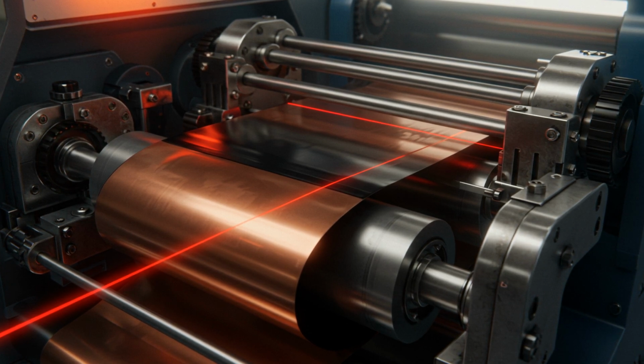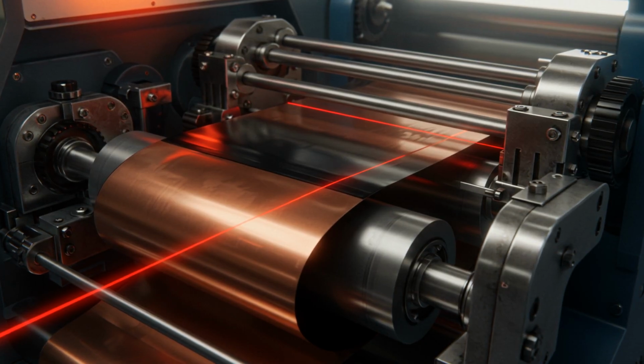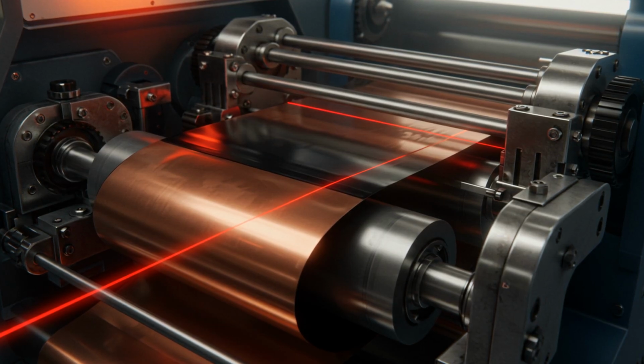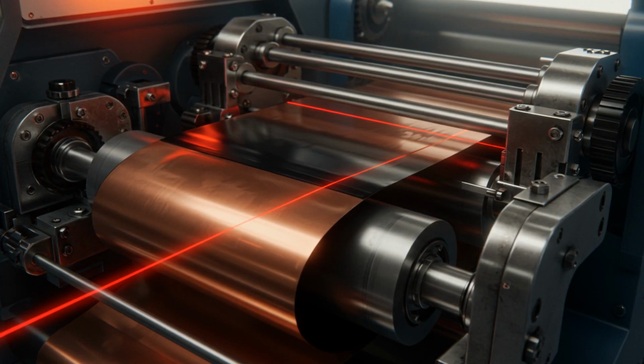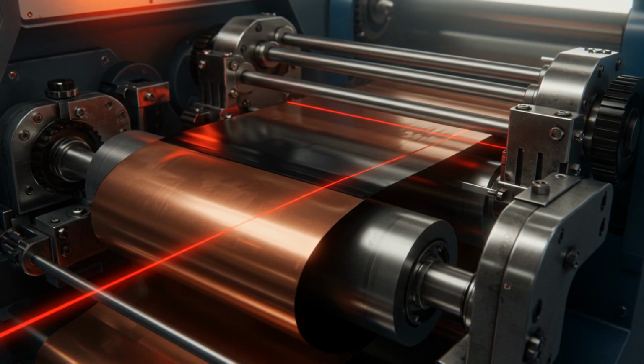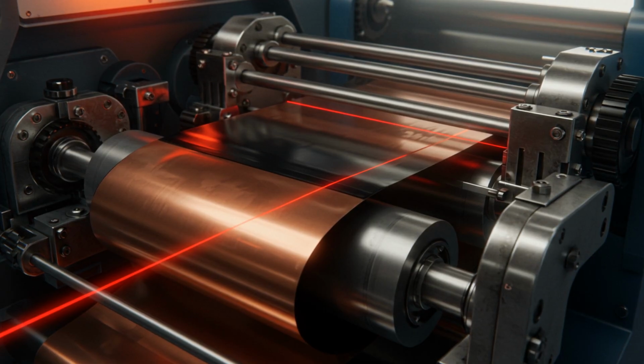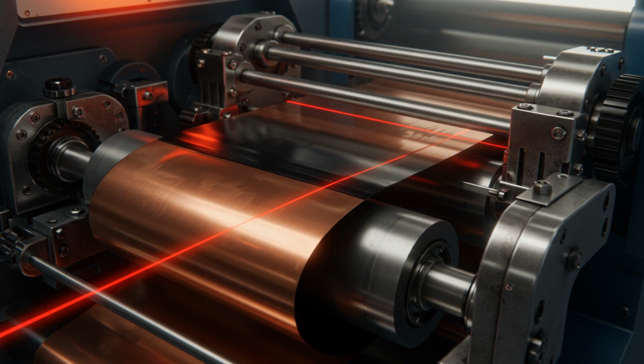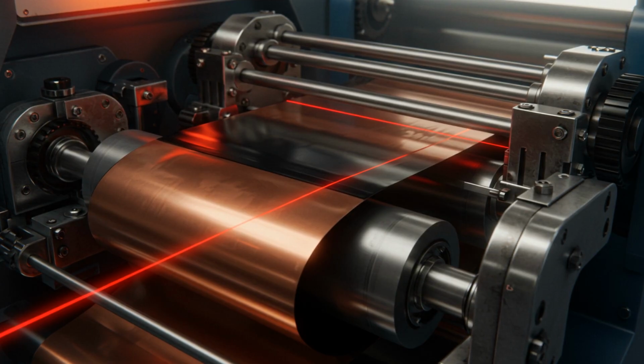If the coating is too thick, the battery might overheat; too thin, and it won't hold a charge. Automated laser micrometers scan the surface every millisecond, adjusting the flow in real time to maintain a tolerance of less than 1 micron. Once coated, the foil enters a massive drying oven several stories high, where the solvents are evaporated and reclaimed. What emerges is a dry, flexible sheet of active material permanently bonded to its metallic carrier. This is the first time the raw chemicals take on a physical structure, a long, dark ribbon of potential energy ready to be compressed and shaped.